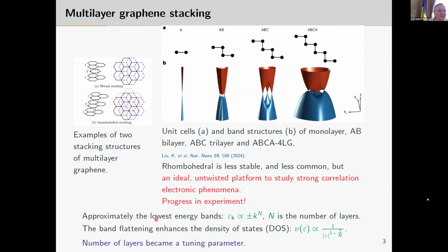And what's theoretically funny about this system? Here is a dispersion law. It's just plus minus k to the power n, where k is a wave vector and n is the number of layers. And why it's interesting: you see that the next equation which I wrote is the density of states, and at some number of layers it already has a singularity. For people who are doing superconductivity, this is how to think about this dispersion: those are approximately flat bands. And from our experience with superconductivity, we know that when the bands are flat, there is enhancement of the density of states, and the BCS equations show a rise of critical temperature. And this explains all the business about flat bands.